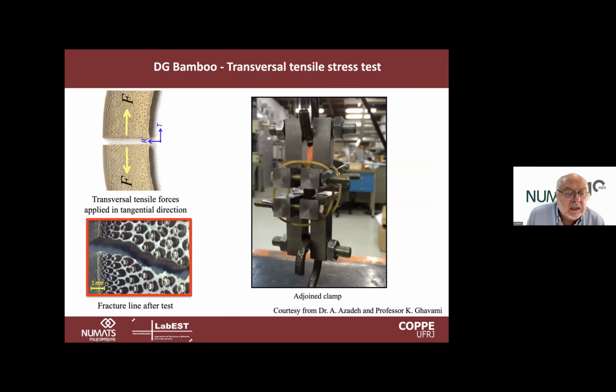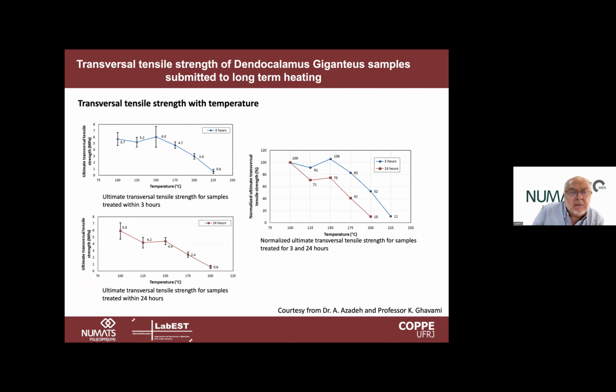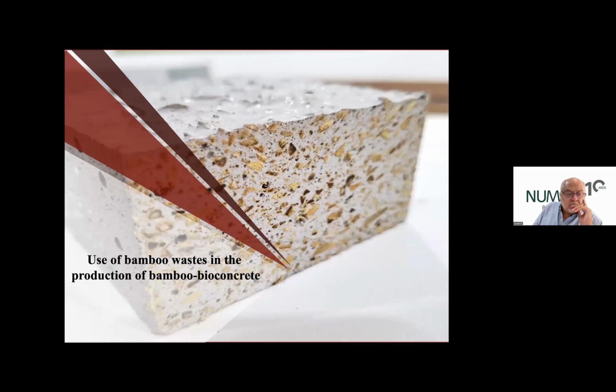We also did this test in the transverse direction. It was just to give an idea about the tensile strength when we test it in the direction where we have nearly no fiber. So this is the matrix strength, and we have only 5%, but the mechanism is the same. The matrix is mainly lignin and pectin, and also after 150 C, we start to see a strong decrease in strength. But of course, if we compare the transverse tensile strength with the direct tensile strength, it's about 30 times less in the transverse direction.